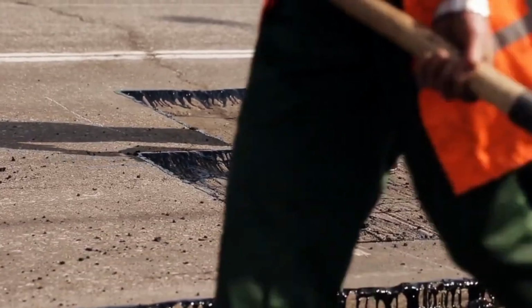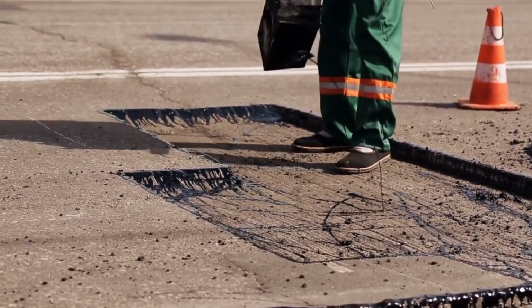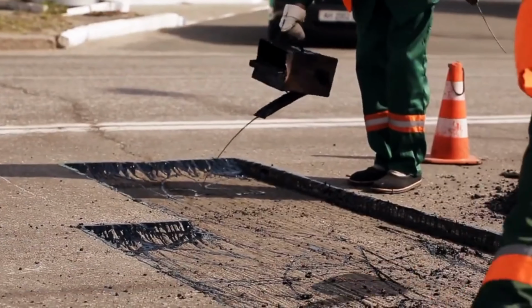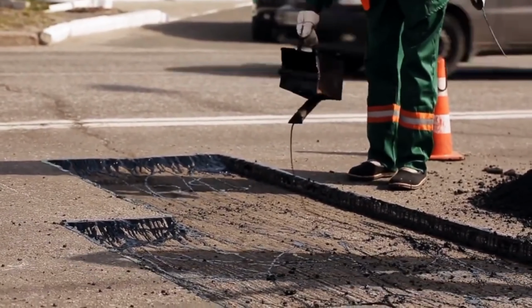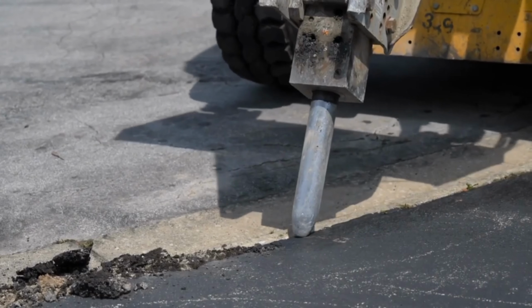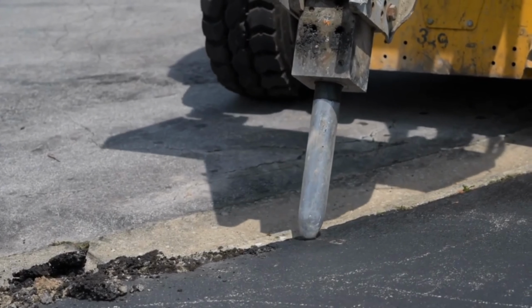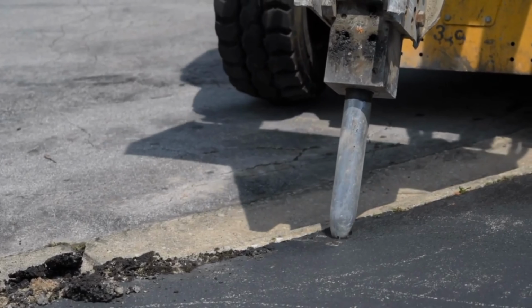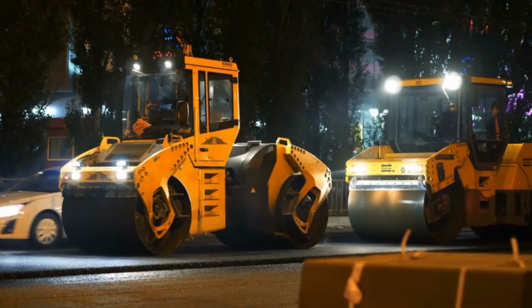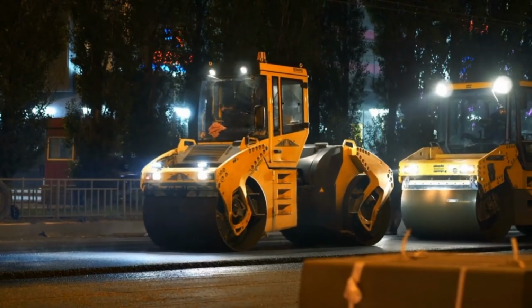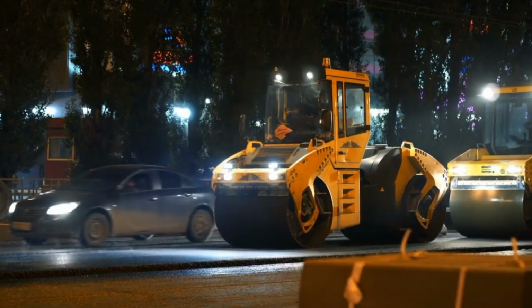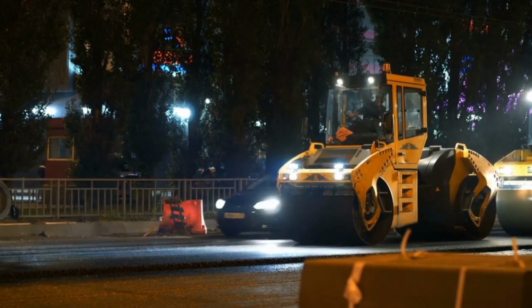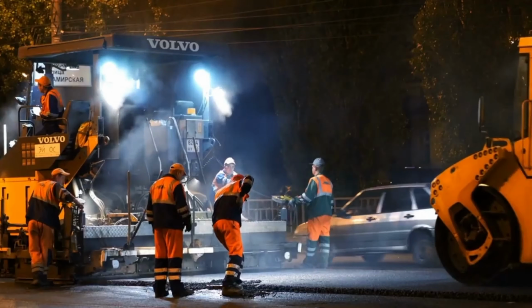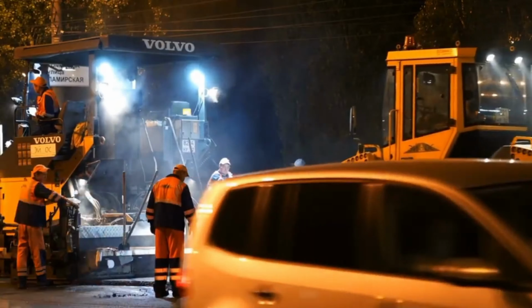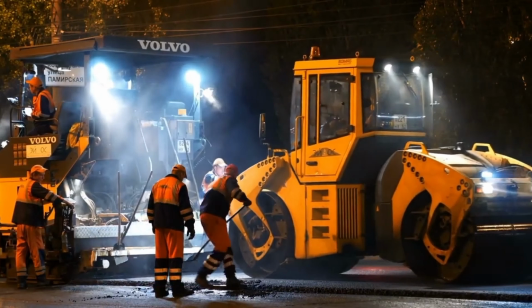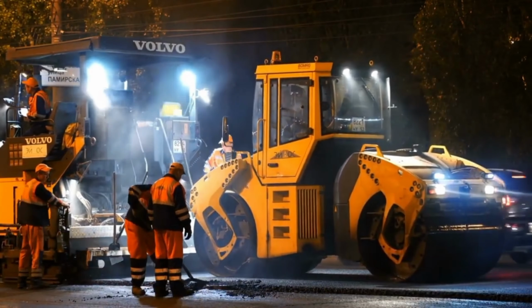Throughout paving, quality control teams take core samples and run density tests using nuclear gauges or intelligent compaction systems. These systems use accelerometers and GPS sensors built into rollers to map compaction quality across the entire road. Lab technicians examine binder content, aggregate gradation, air void levels, and asphalt temperature. Any deviation triggers adjustments on the fly, ensuring every stretch of highway meets exact engineering standards.